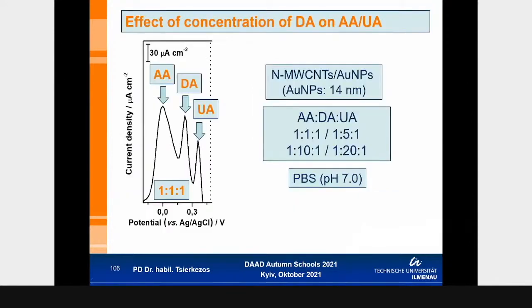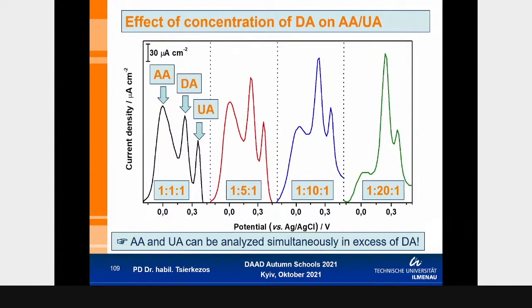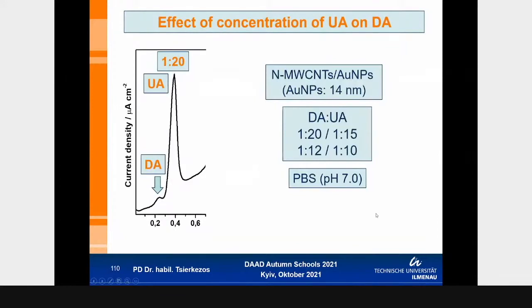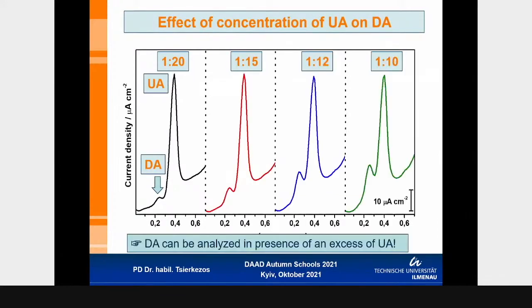So we have investigated further the effect of the concentration of dopamine on the oxidation of ascorbic acid and uric acid, and we have increased the concentration of dopamine up to 20 times greater than that of ascorbic acid and uric acid, and you can see that even when the concentration of dopamine is 20 times greater, you can still see the peaks of both biomolecules, which means that the ascorbic acid and the uric acid can be analyzed in the presence of an excess of dopamine. The same has been done for the effect of the concentration of uric acid on dopamine. You can also see here that the dopamine peak can be detected even if the concentration of uric acid is about 20 times greater than that of dopamine.